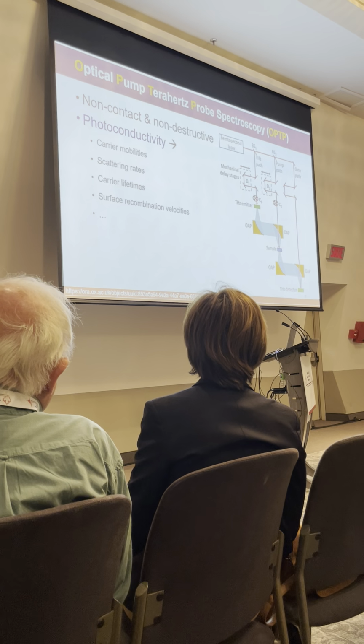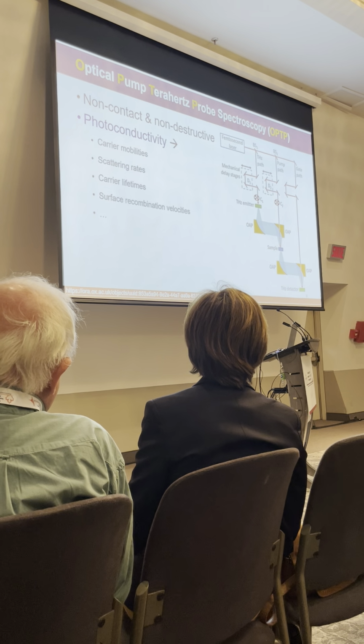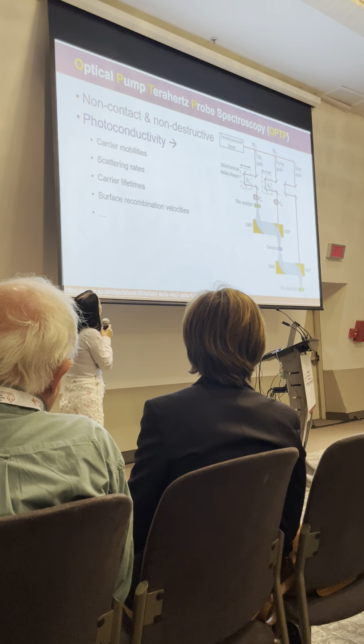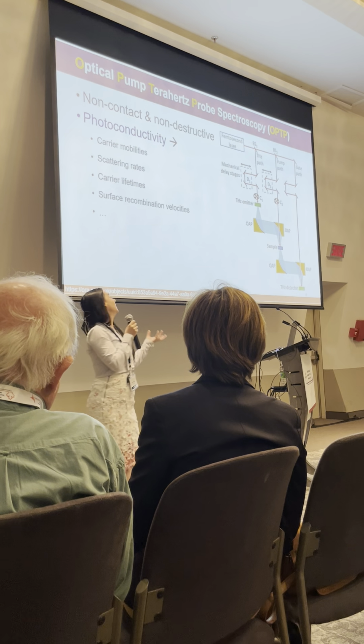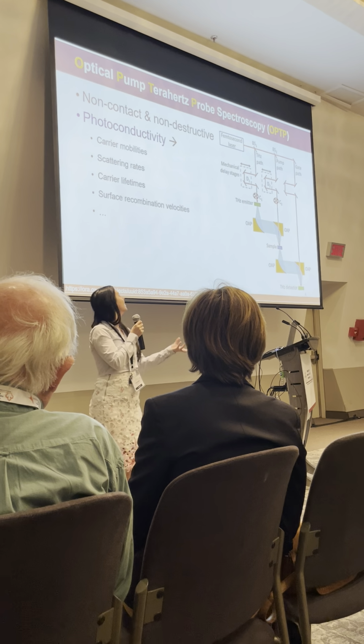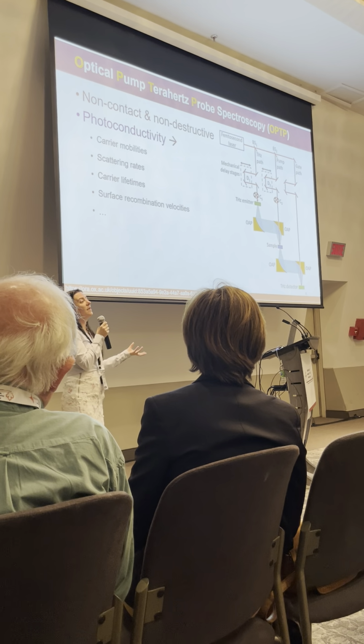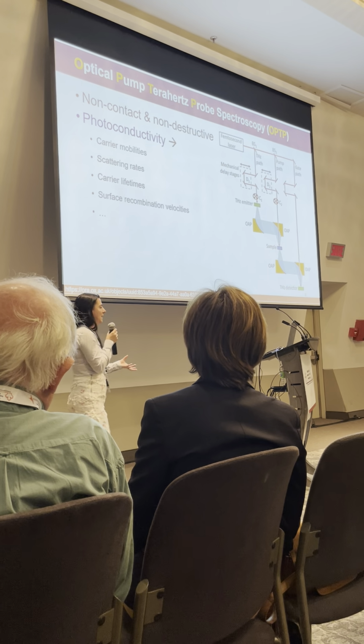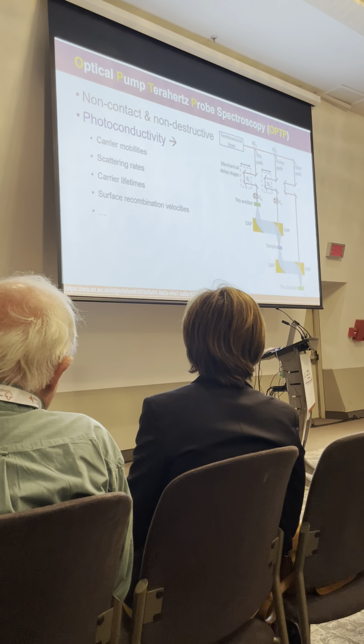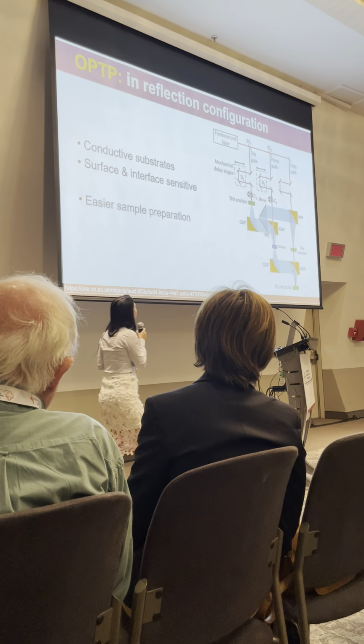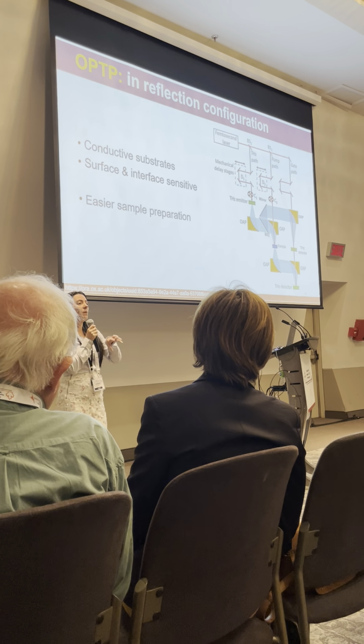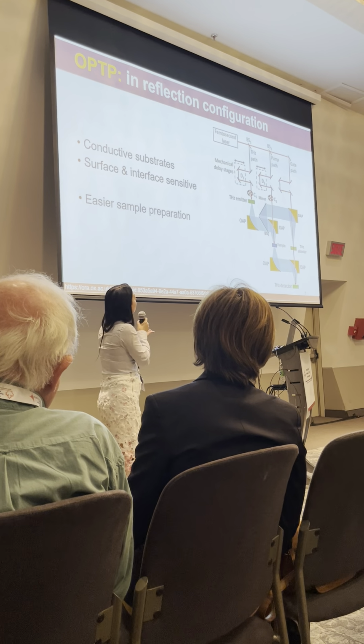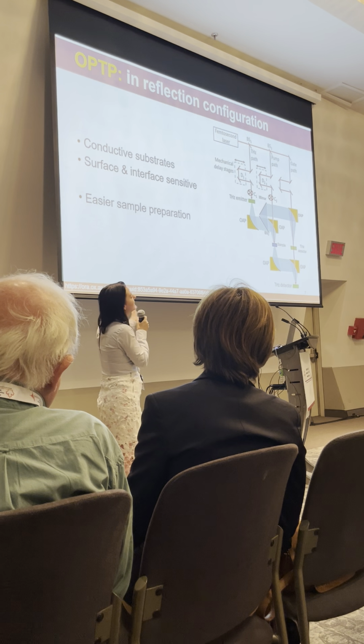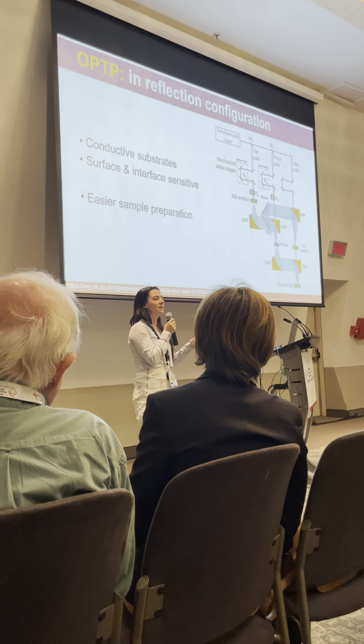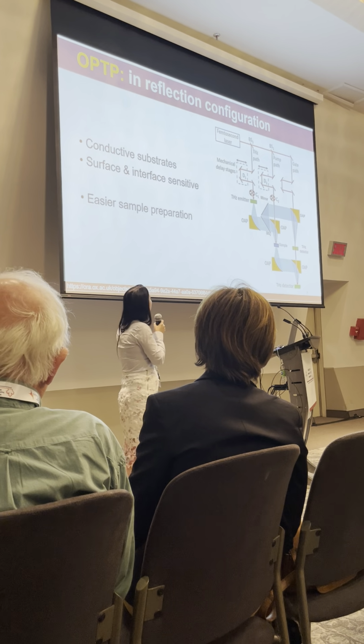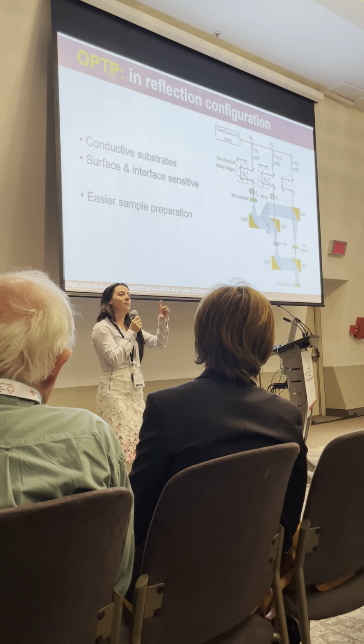But in both systems and both ideas of this spectroscopy, we can still get ideas about carrier mobilities, scattering rates, carrier lifetimes, and surface recombination velocities. So both are going to be really good as a non-contact probe for that. But we have to bear in mind that when we're in reflection configuration, we need to be careful if our substrate is conductive. We also need to think about what our probing depth is.